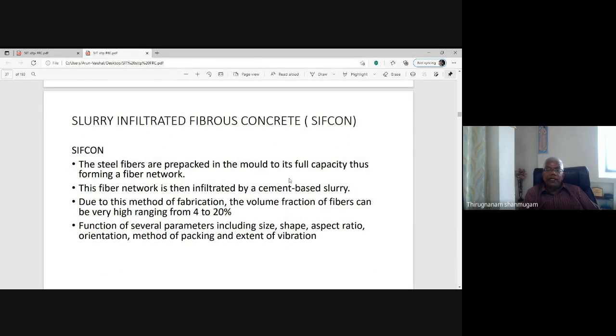In SIFCON, the steel fibers are pre-placed in the mold to its full capacity, thus forming a fiber network. This fiber network is then infiltrated by cement-based slurry. Due to this method of fabrication, the volume fraction of fibers can be very high, ranging from 4 to 20%. Normally, 10% volume fraction is adopted easily. Beyond 10%, the flowability of the slurry becomes very thin, and you have to add superplasticizer along with VMA, etc. So for normal purposes, 8% or 10% volume fraction is sufficient. This is a function of several parameters, including size, shape, aspect ratio, orientation, method of packing, and extent of vibration, etc.